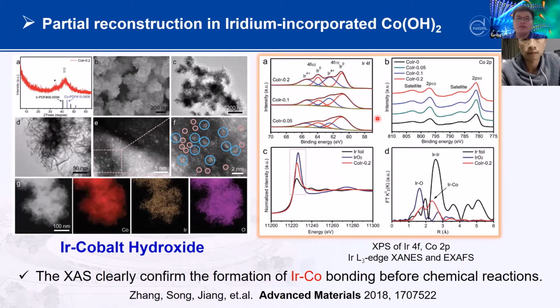As you can see, we made a model catalyst. We put iridium incorporated with cobalt hydroxide. Before the reaction, of course they do have very tiny atoms here, but in most cases they have some clusters, so we call this a nanocluster. Before the reaction, you will see by XPS and also by XAS that they show a very clear iridium nanocluster with cobalt hydroxide. That means you will see very clearly a tiny iridium-cobalt bonding, which comes from the support and interface.